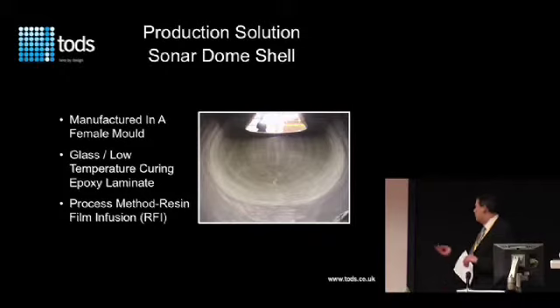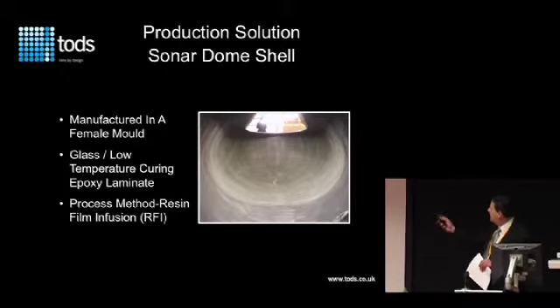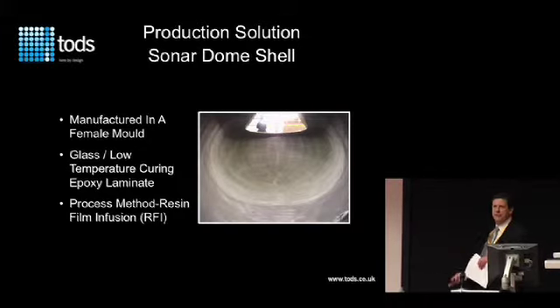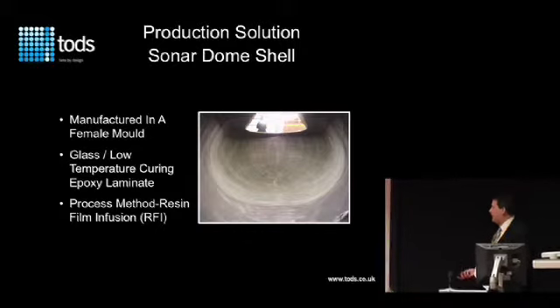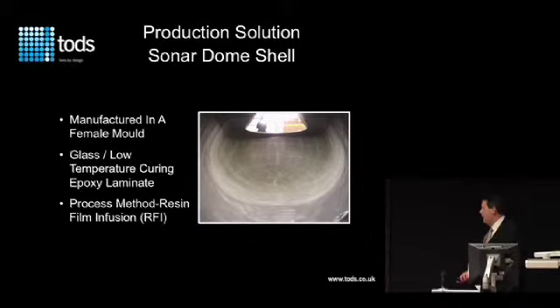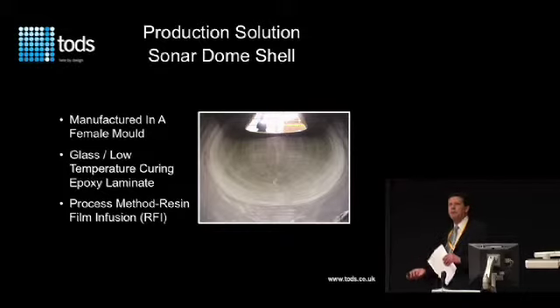Now, this is a completed dome, and you can see the difficult shapes that you've got to deal with. So when I was talking earlier about how much tack and how easy it is to hold things into position, that's a major issue for us. We decided that we would manufacture it in a female mould using glass RFI. Principally, we could have achieved the quality that we required using low temperature prepreg, but because of the debulking operations, where you'd be debulking this every day, economically it just wasn't viable. The time to achieve and the cost of achieving it would have been too much.